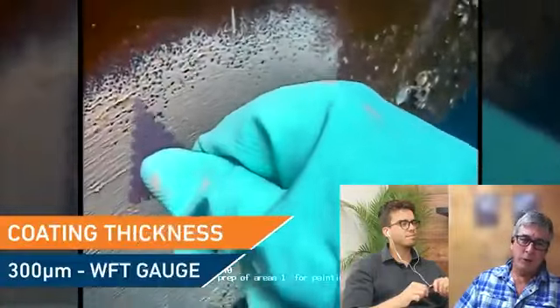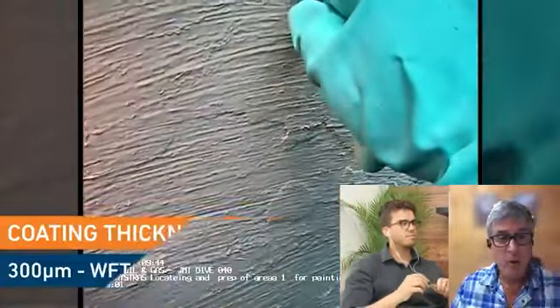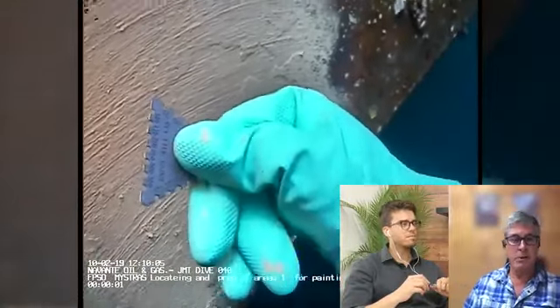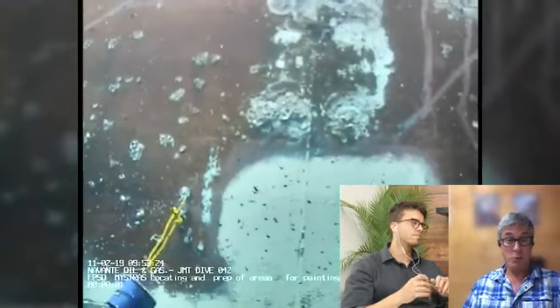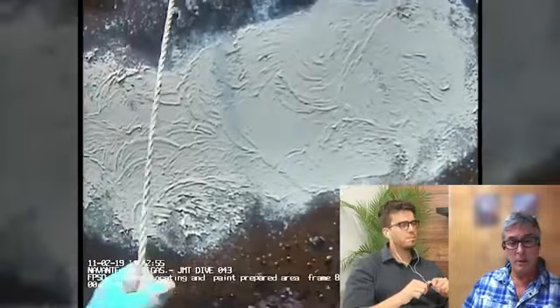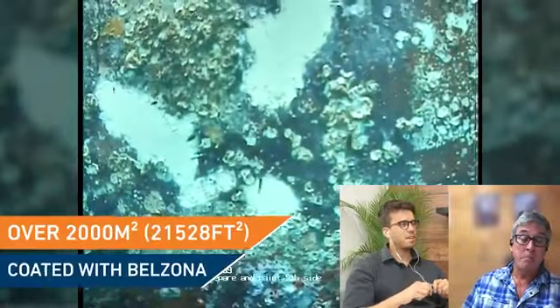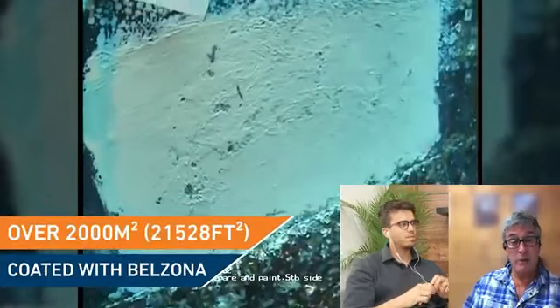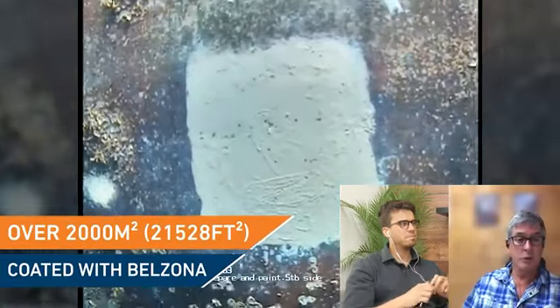In terms of value, often we're painting large areas. It's not all corrosion. We're painting large areas simply because the existing coatings are delaminating. The anti-fouls come off. We've lost coat 3 on an international product. Not all these coats are put on properly when they're painted on ships in foreign ports. So we prepare the areas where we have corrosion. We remove all loose coatings down to something which just isn't going to come off with a great deal of effort. That's where you leave it, because you don't want to take off paint that's stuck onto the side of the shell plate properly.